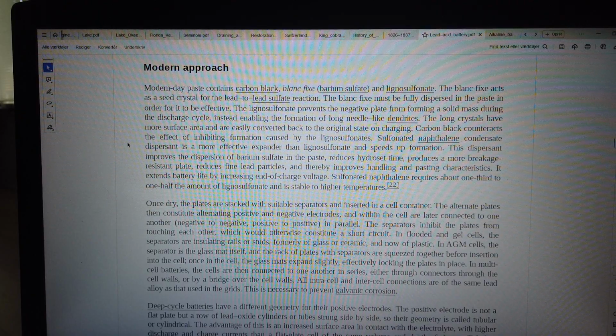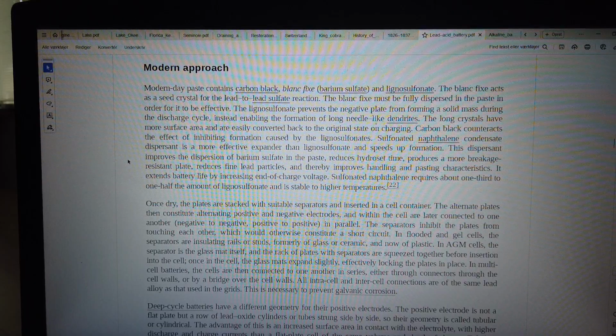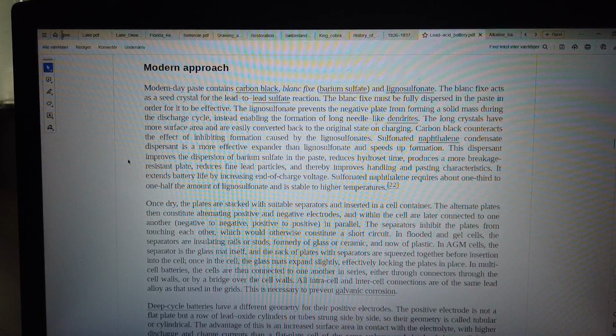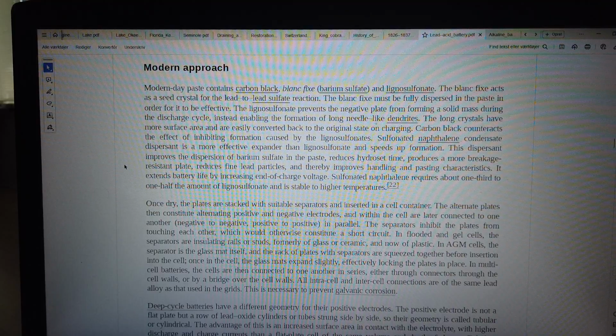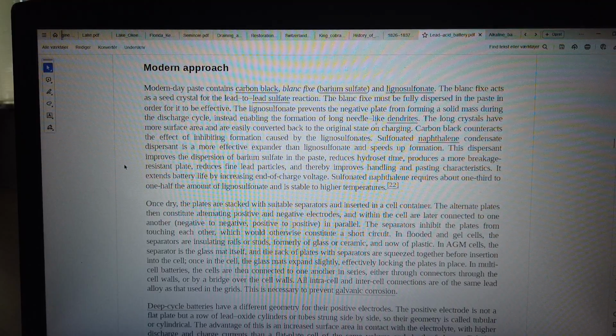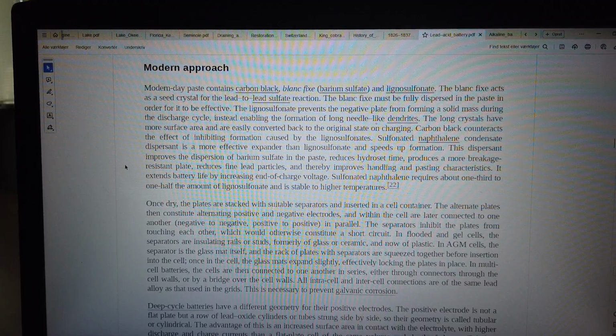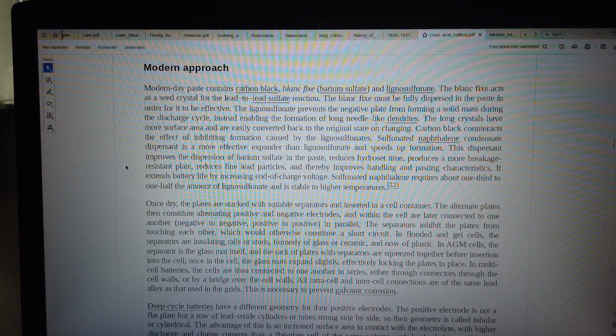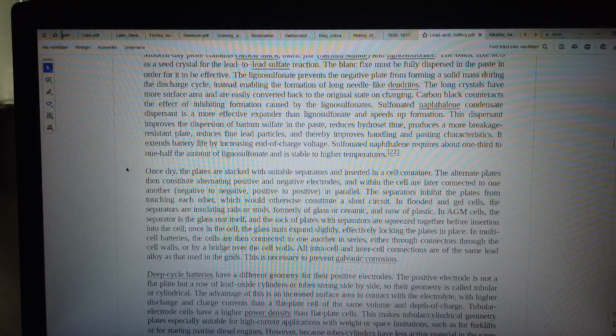Sulfonated naphthalene condensate dispersant is a more effective expander than lignosulfonate and speeds up formation. This dispersant improves the dispersion of barium sulfate in the paste, reduces hydroset time, produces a more breakage-resistant plate, reduces fine lead particles, and thereby improves handling and pasting characteristics. It extends battery life by increasing end-of-charge voltage. Sulfonated naphthalene requires about 1/3 to half the amount of lignosulfonate and is stable to higher temperatures.